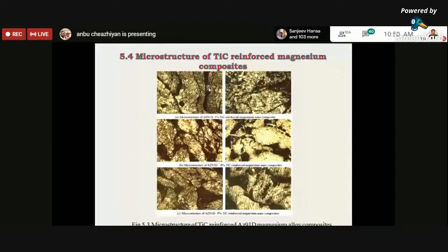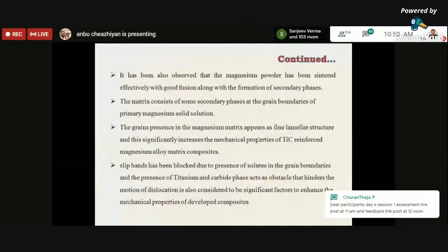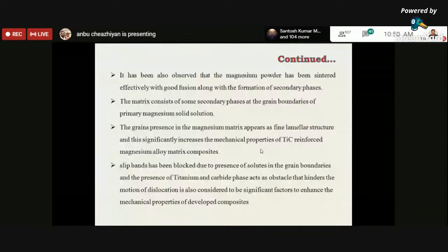The grains present in the magnesium matrix appear as a fine lamellar structure, and thus significantly increase the mechanical properties of titanium carbide reinforced magnesium alloy composites. It is also noted that the slip bands are blocked due to the presence of solutes in the grain boundaries, and the titanium and carbide phase acts as an obstacle that hinders the motion of dislocations. It is considered a significant factor in enhancing the mechanical properties of the developed composites.